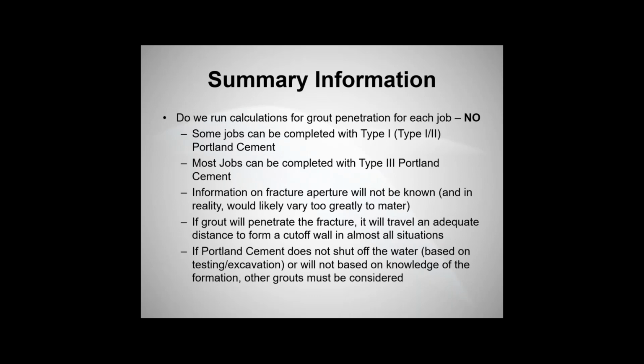One of the main reasons is simply that you'll probably never have good information on the aperture width for a grouting job, which was the first equation, the groutability equation. I've been doing this for almost 20 years, and if I have any information on aperture width, it's generally something like large, small, 6 inches. It's not really applicable to what we're doing as far as the calculation goes.